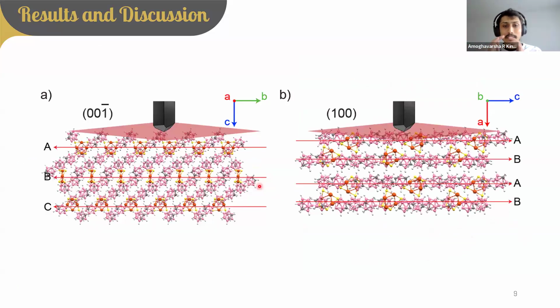When we observe the crystal packing along the direction perpendicular to the indentation direction, we see that in Cu4 OCBT, the clusters are arranged in an ABC plane fashion, but the ligands are arranged along slanted planes like this, and the intercluster interactions involved in these clusters are along these slanted planes and are not along these ABC planes.